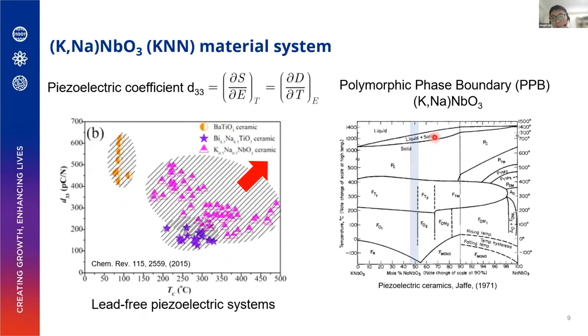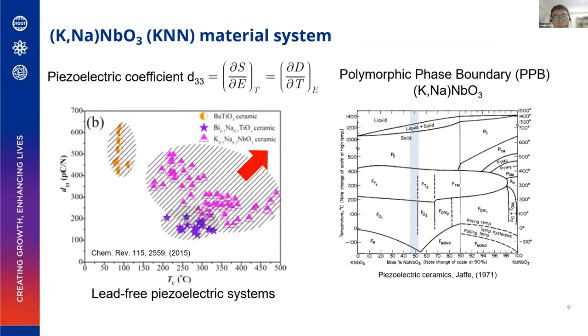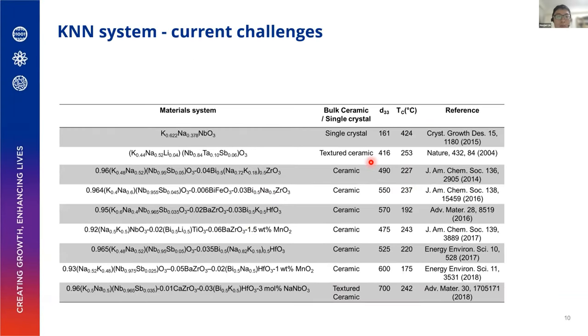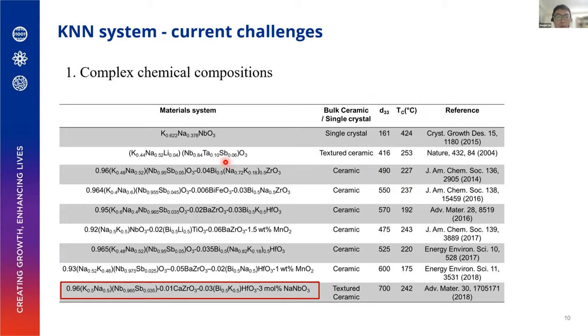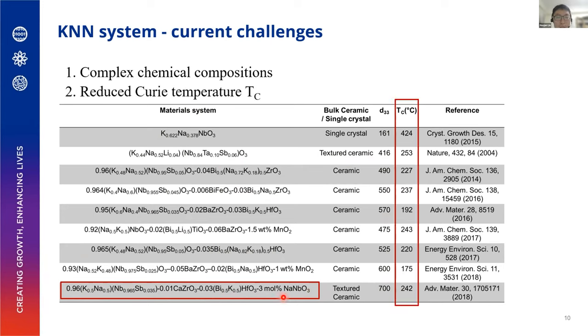This is formed by a kind of polymorphic phase boundary between potassium niobate and sodium niobate. At this particular composition, you can have an enhanced piezoelectric response. But the challenge in this material system is that people are trying to dope more elements into this material to improve the piezoelectric coefficient. This comes at the price of very complicated chemical compositions, which are very difficult to reproduce. Another side effect is that when you dope a lot of elements into this system, your Curie temperature keeps dropping because you're breaking the original lattice of this material.